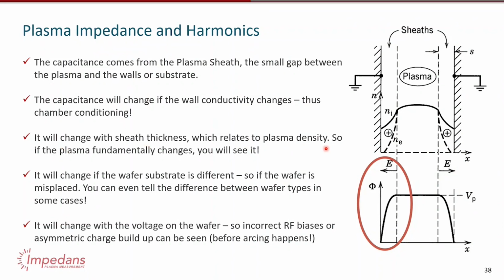The sheath thickness depends on plasma density. So if for some reason your generator calibration is off, or your matchbox is off, or there's something that's affecting your plasma density, you see a change in the capacitance, you see a change in the plasma impedance. So if plasma density changes, you will see it with a VI probe. Additionally, this may surprise people, but the wafer itself is like a capacitor. Okay. So for example, if the wafer is not sitting correctly on the electrode, you get a totally different capacitance, totally different sheath shape, and you can detect that using the change in the impedance of that circuit. Okay, and we've set up alarms in facilities for wafer misplacement based on these techniques. Even things like charge buildup on the wafer may change the voltages, and so on.